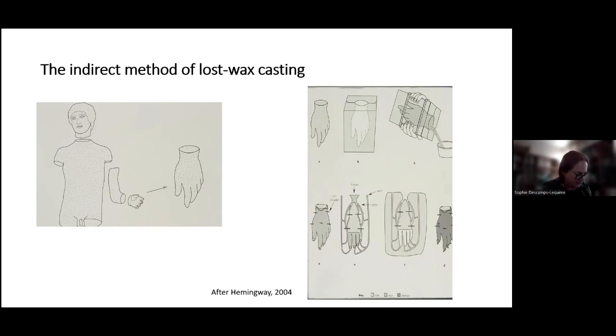These beeswax sections of the statue were reassembled into a working model which could be detailed by the bronze worker, the sculptor himself in the classical period. The bronze maker moved closer to the maker of clay figurines and vase figures and became truly a plastes, as the creative gesture came under the heading of modeling. This word plastes was used by Plutarch to describe Polycletus. In the 5th century BC, bronze sculptors were modelers, and this happened twice, when they modeled the clay prototype and when they added wax details such as curls of hair, beard on the wax working model.